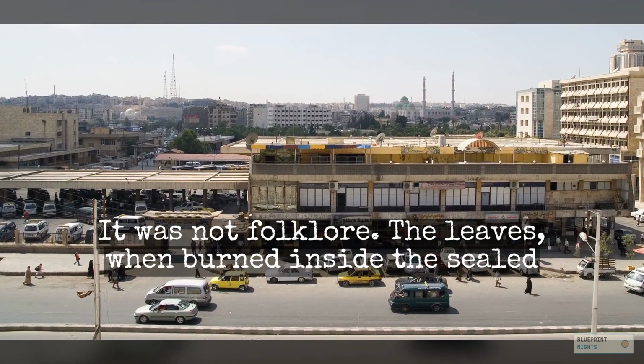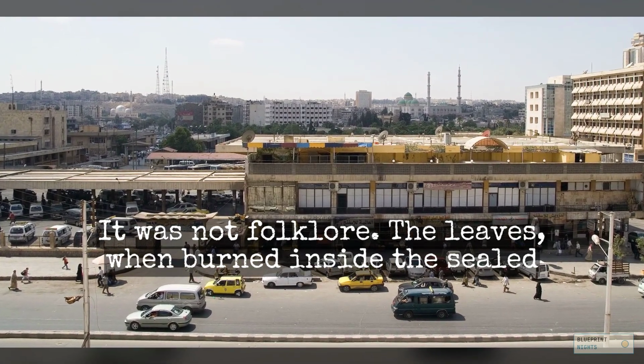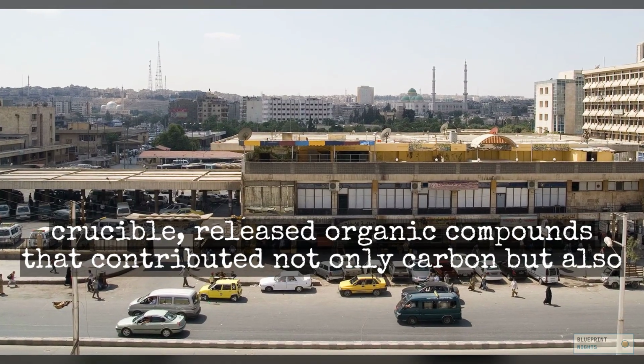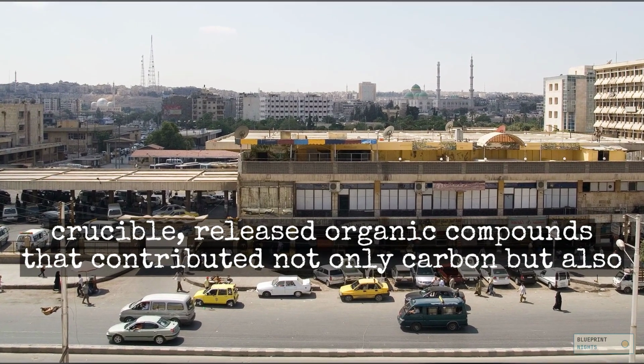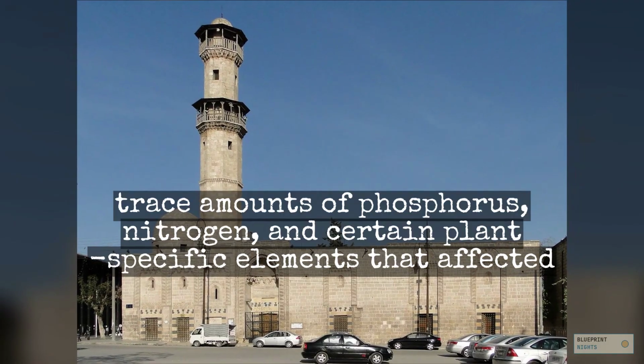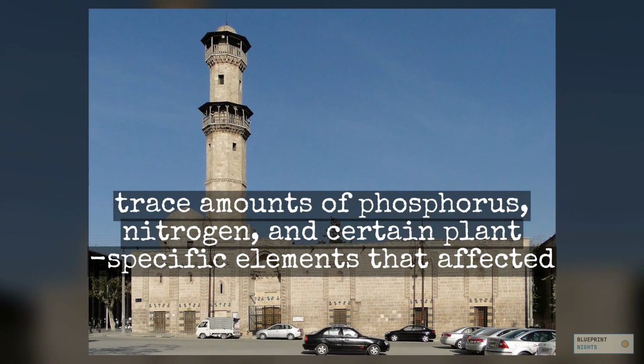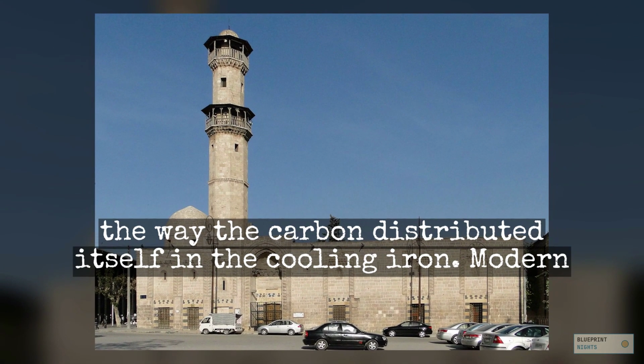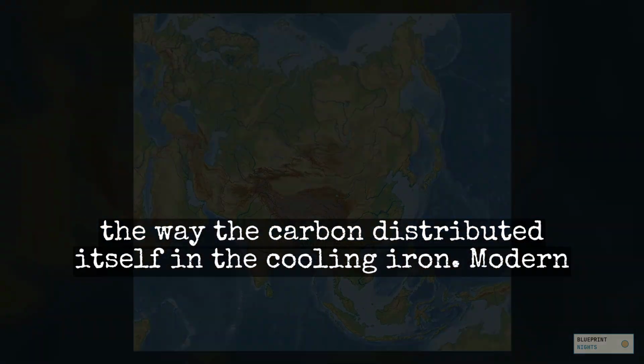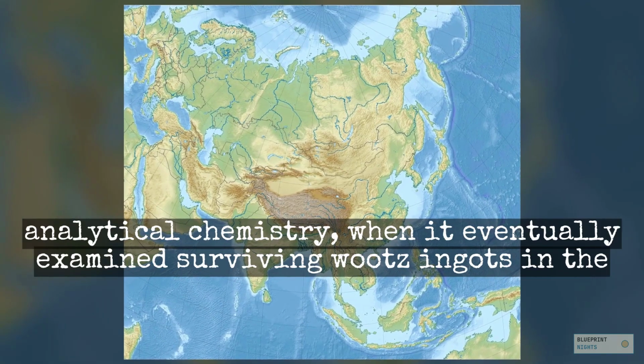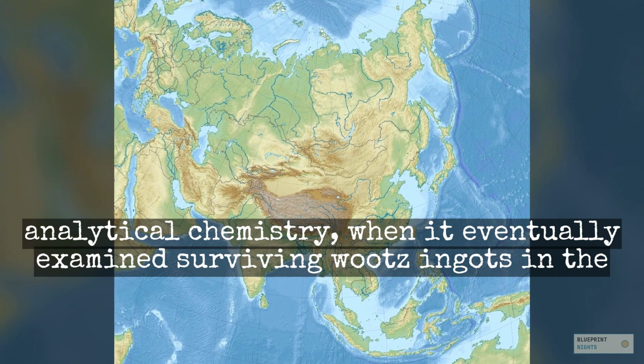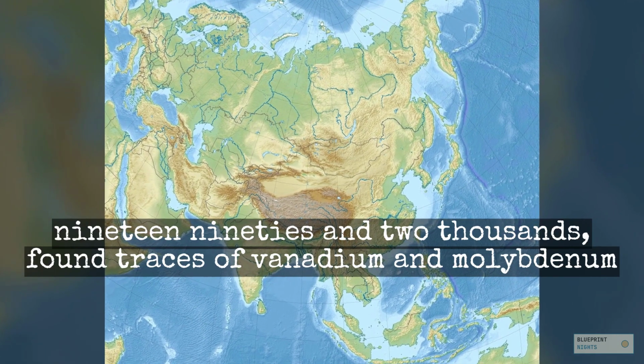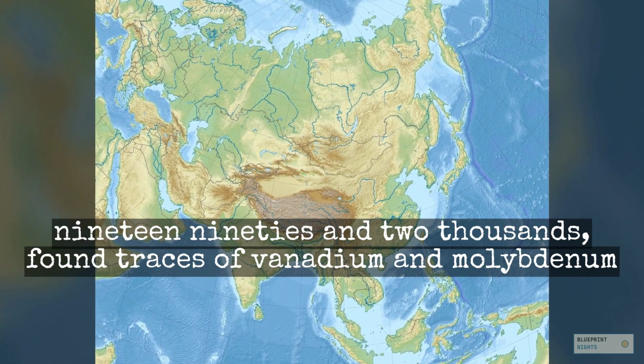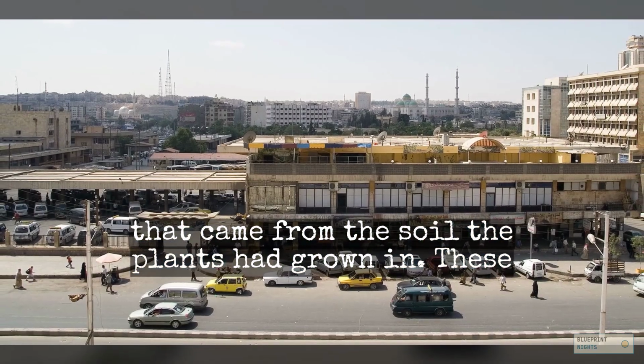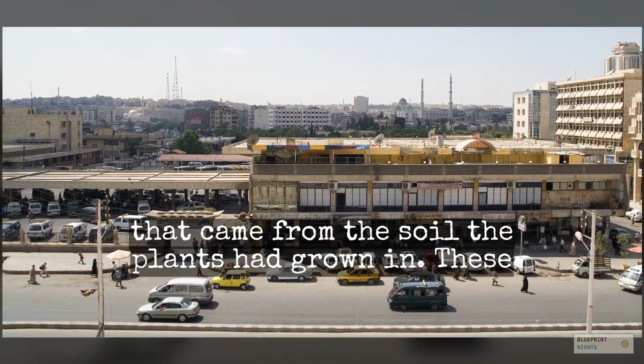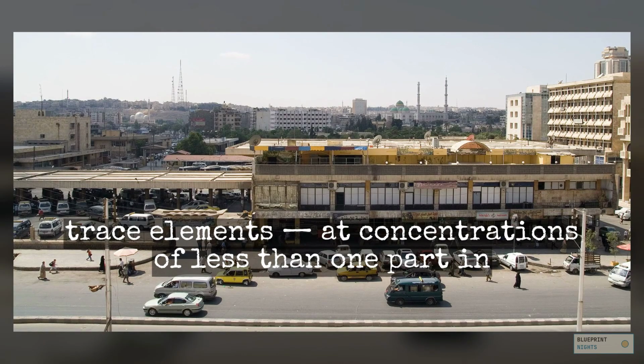It was not folklore. The leaves, when burned inside the sealed crucible, released organic compounds that contributed not only carbon, but also trace amounts of phosphorus, nitrogen, and certain plant-specific elements that affected the way the carbon distributed itself in the cooling iron. Modern analytical chemistry, when it eventually examined surviving Wootz ingots in the 1990s and 2000s, found traces of vanadium and molybdenum that came from the soil the plants had grown in.